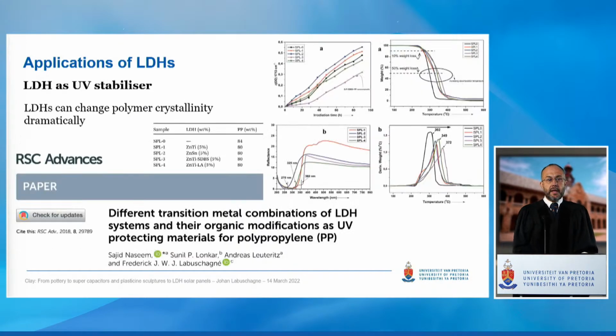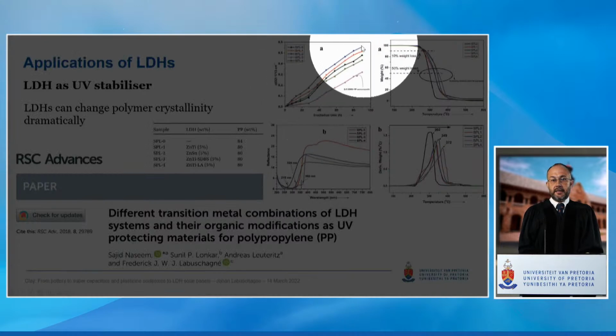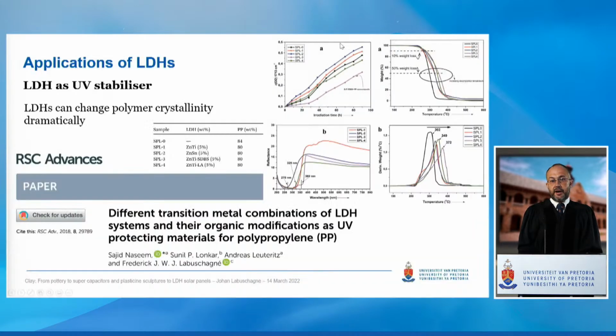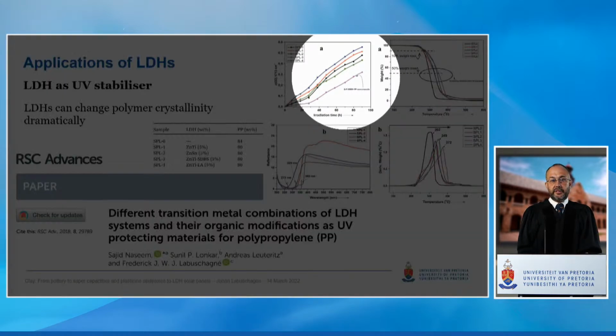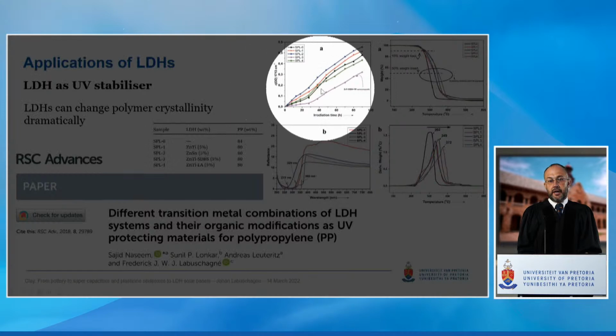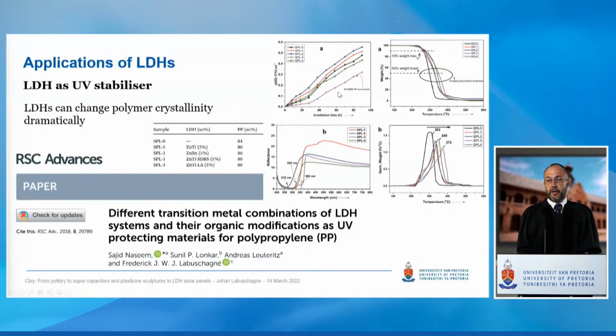In this publication, in collaboration with my collaborators at the IPF in Dresden, we looked at the UV stability of different LDHs. In this graph, the SPL0, so that is the top line here, is the neat polymer with no loading. And right at the bottom, going top to bottom, are different polymer loadings with different LDHs. And it's clear that there's a drastic increase if we take from there for a certain loading, the time to degradation of the polymer. The other graphs just show how the degradation peaks on the DSC and the TGA moved.